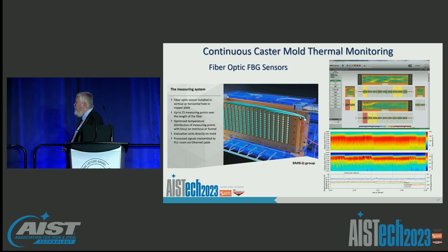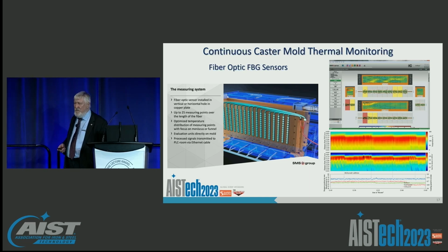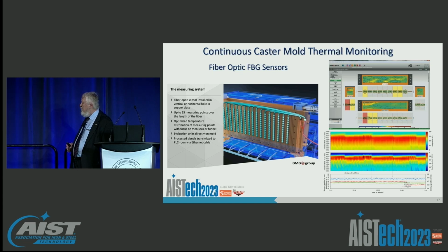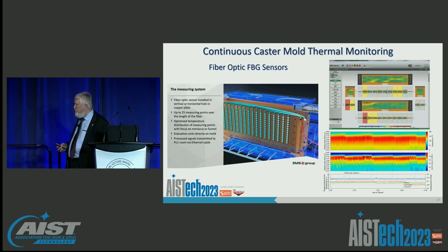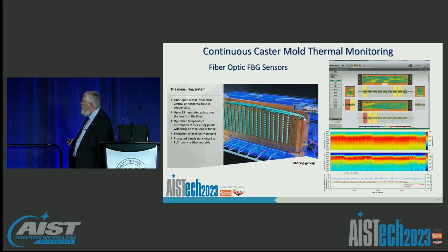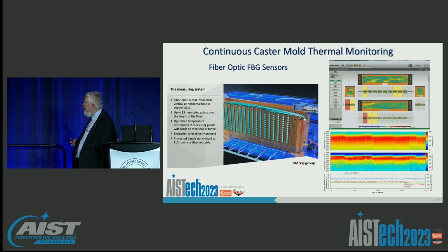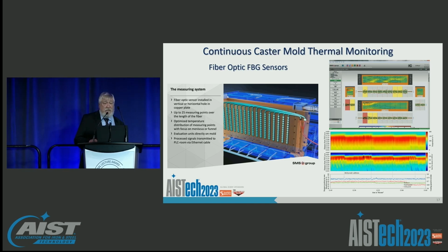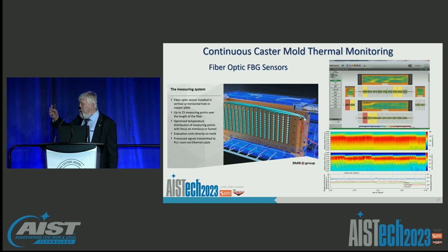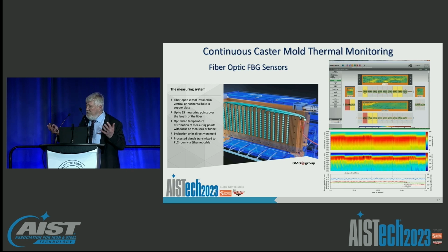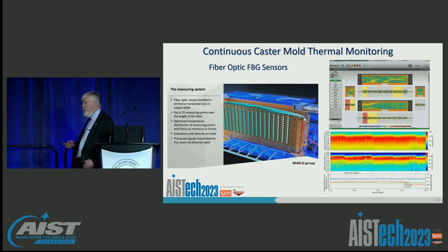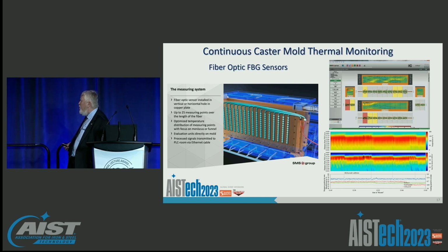One of the biggest areas we're seeing an influx of fiber optics is in the continuous casting process for measurements of mold thermal behavior. And the standard right now for these technologies are based generally on fiber optic sensing methods using Bragg gratings. These Bragg grating methods, as I mentioned, can measure resolutions down to about 5 millimeters and can map the thermal behavior in a mold over a wide area. Here, each trace has a number of sensors on it, and each trace is an individual fiber feeding one line in this case. That information is taken back and converted into a thermal map, and these things are used not only for sticker detection in continuous casting, but also thermal monitoring to essentially evaluate mold thermal behavior, flux behavior.